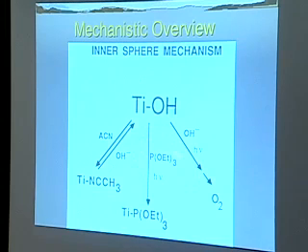Okay. On the other hand, you could take another material like this phosphite, and we happen to pick this because it's water soluble. And when that binds to a titanium site, it would make this species, and that species would not compete with hydroxide. That is, that binding is much stronger than hydroxide binding. So one would think if you had an inner sphere mechanism and you threw your electrode into this stuff, that you would kill your electrode. You couldn't oxidize water, or hydroxide rather, anymore with that.